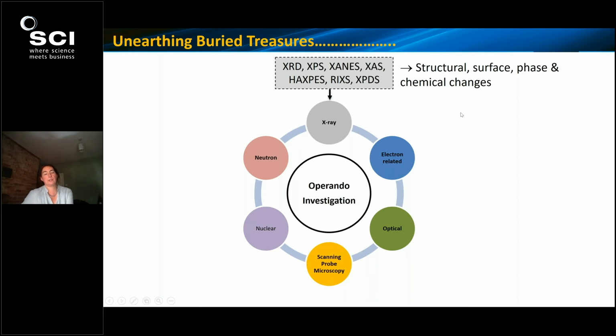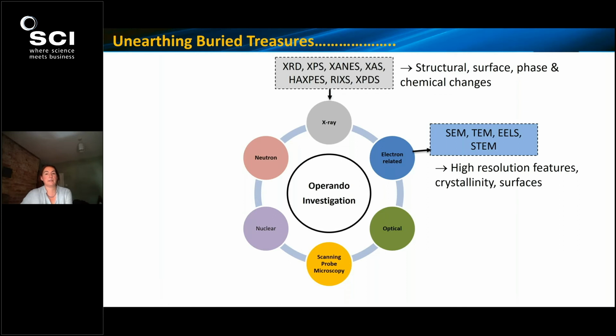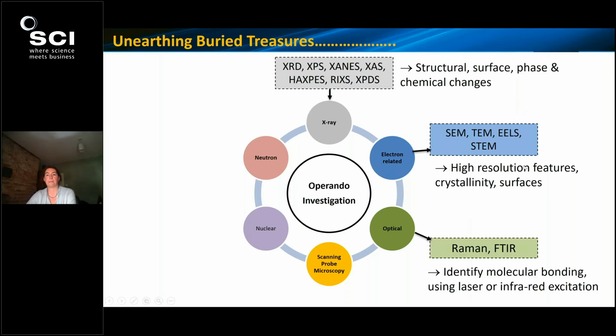the X-ray sources. Techniques such as XRD and XPS, which are X-ray diffraction and X-ray photoelectron spectroscopy, have given us a lot of very valuable information about structural phase changes, surface, and indeed chemical information. Electron-based techniques are imaging or high-resolution imaging techniques such as SEM and TEM, which can give us good feature information as well as crystallinity properties and surface information on topography, etc. Optical-based techniques can identify molecular bonding and are typically Raman or FTIR type techniques that use laser or infrared excitation respectively.